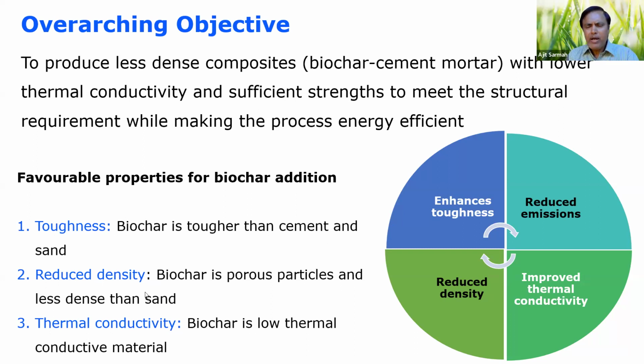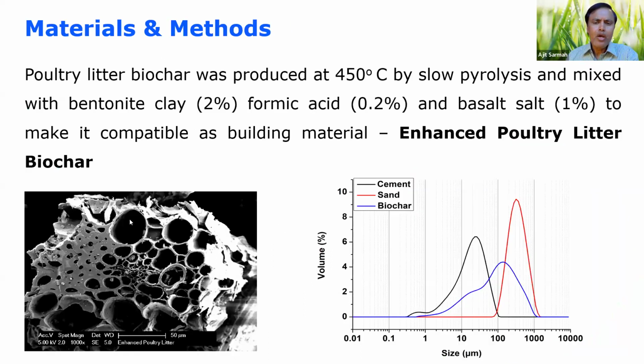Biochar is very light, so you need a huge volume. So it reduces the density, and biochar is a low thermal conductive material. These are the favorable properties of biochar that you can make use of when you produce mortar or concrete. It will enhance the toughness, reduce emissions, reduce density, and also improve thermal conductivity. So what we did, we used poultry litter biochar, which was produced at 450 degrees Celsius by slow pyrolysis. This is a scanning electron micrograph of poultry litter. And we mixed that with bentonite clay, formic acid, and basalt dust to make it compatible as a building material. And then we also looked at the particle size distribution here.